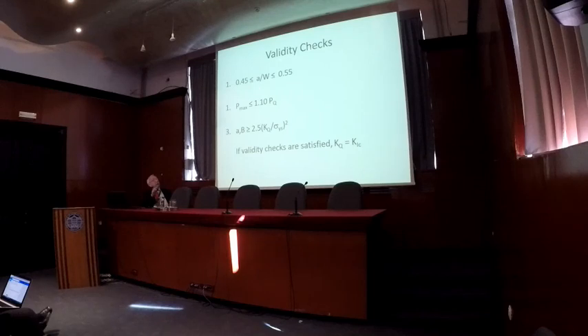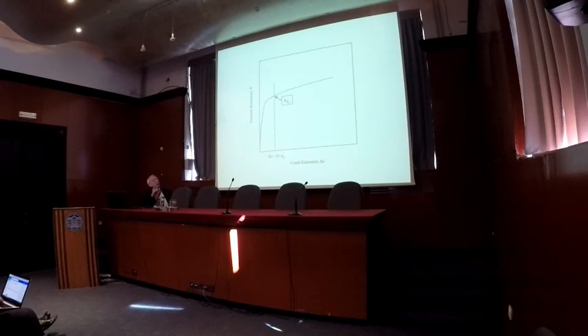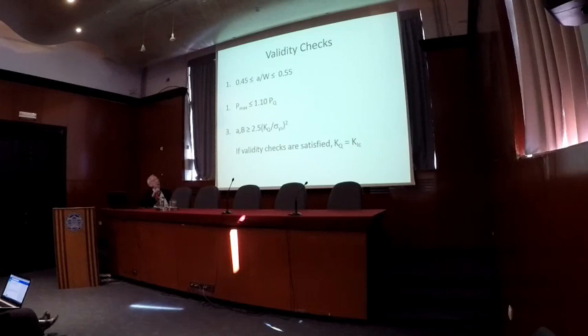And then you need validity checks, and there are three main ones. One is that the crack length is essentially half of the width W. This one then says the maximum load here should not be more than 10% greater than the PQ. And then finally, you have a criterion that says 2.5 times (K over the yield strength) squared, and that is related to the plastic zone. So that essentially says that the plastic zone should only be about 5 or 6% of the total width.